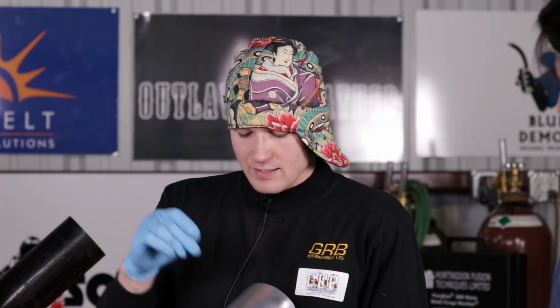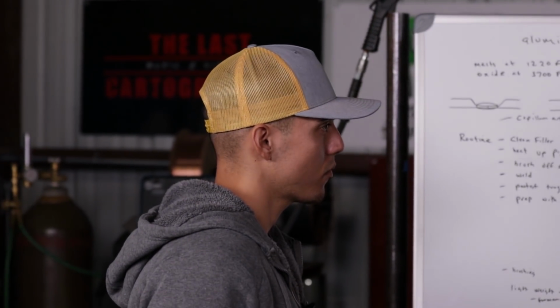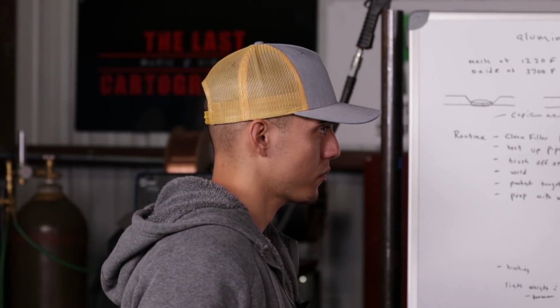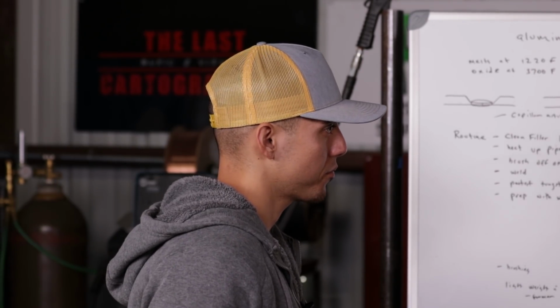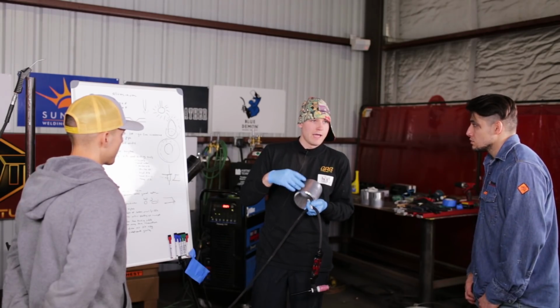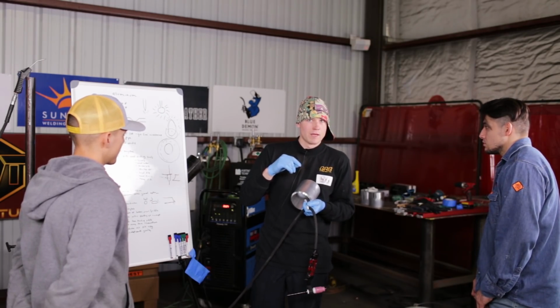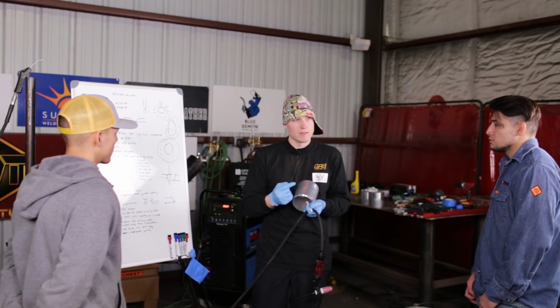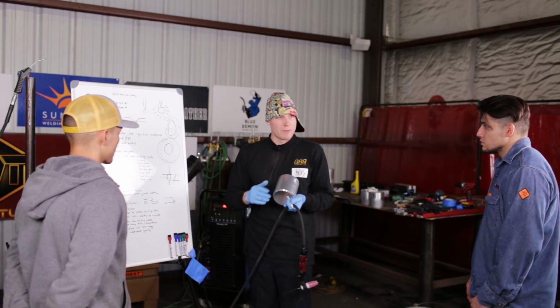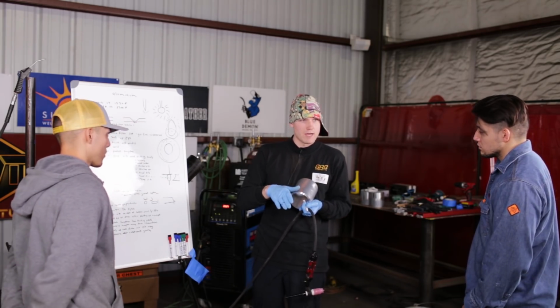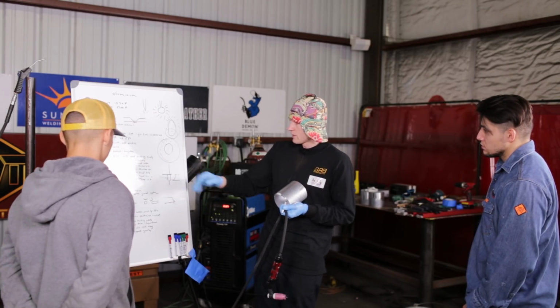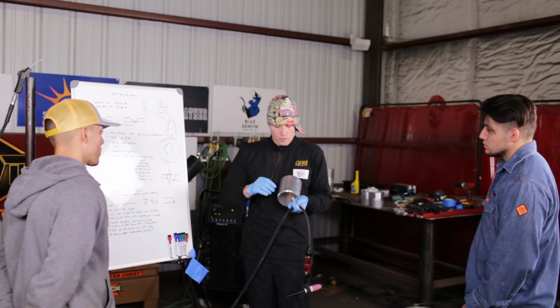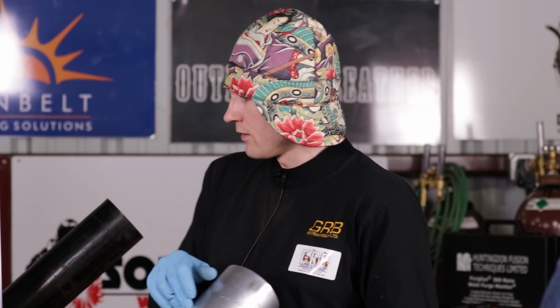Yeah. But the second it touches, it makes a huge little micro explosion, and you get black soot everywhere, and it contaminates the tungsten, contaminates the weld zone, and it embeds. You can embed tungsten into the material. It contaminates the aluminum and contaminates the tungsten as well. So everything is basically contaminated. That metal has to be removed with woodworking tools, a wood router, or a file, because when you file it, you will find embedded tungsten in the aluminum material.